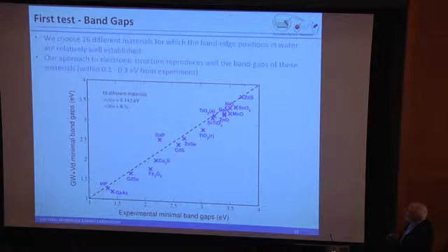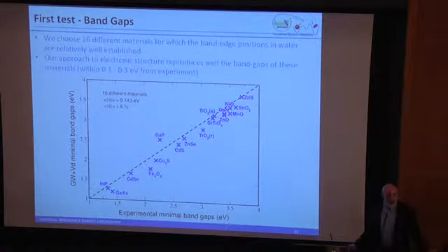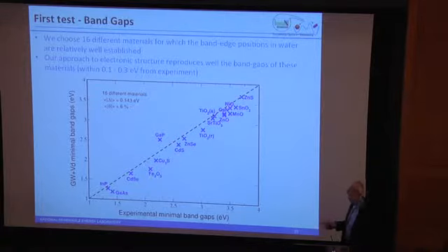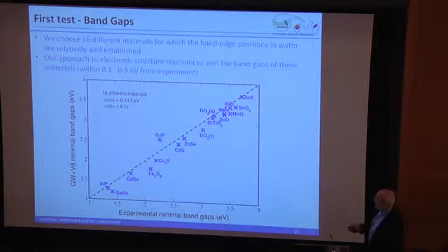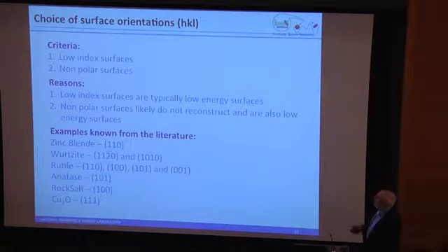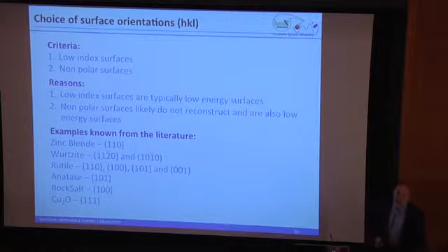But the bottom line is if you do this and you take that same kind of plot that we showed before and you look at it, we can now plot basically a straight line for oxides and non-oxides together. And so it looks like it really does work in predicting where you'd expect the band gap and the minimal band gap to be. So then we have to look at surface effects. And what we did is we assumed that we would use low index surfaces initially and or non-polar surfaces, because these are typically what you find in these materials. And we know non-polar surfaces don't reconstruct a lot, and they're also low energy.